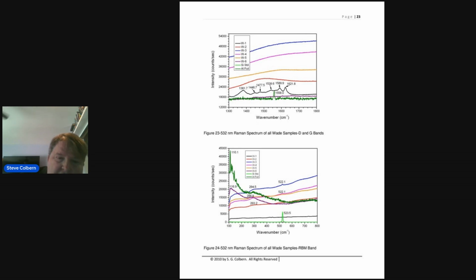it'd be very interesting to dissolve some of this material in acid and see if any carbon nanotubes were left behind. If I were going to go back and retest these samples, that was one of the things I would do. Carbon nanotubes are also very resistant to chemical dissolution or oxidation. They survive in air up to about 500 degrees Celsius or higher. And in vacuum, they'll go up to like 2,000 degrees Celsius. They're very, very stable and very strong. And you can change the electronic properties of them by putting different metals inside. I actually have a patent on that.